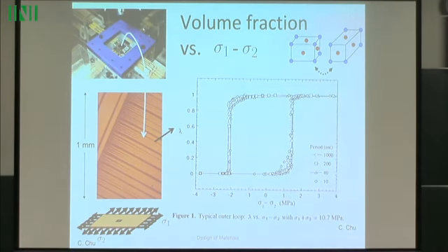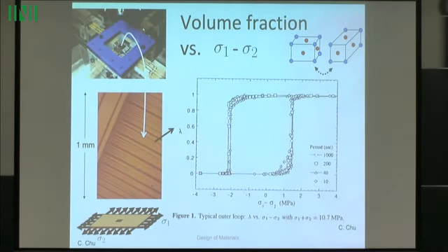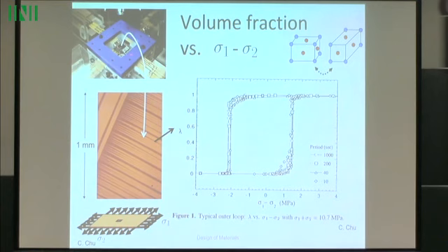Let me come back just to that stress hysteresis case. I'm looking at this case right here, and in fact that was done with a biaxial testing machine. That's why sigma 1 and sigma 2 are the stresses on the two axes, and the microstructures during transformation look like this. This was a dead load biaxial testing machine, which had a special property that homogeneous deformations are stable states in this machine. So it passed from one homogeneous deformation to another by applying the loads.